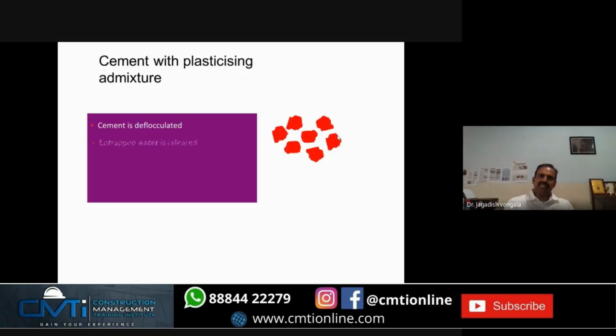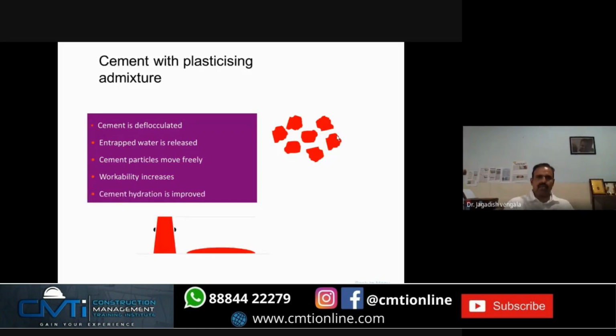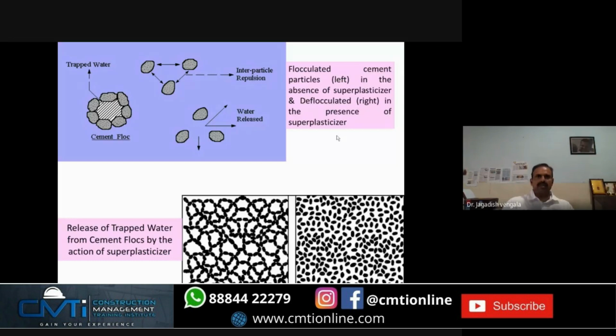So by adding plasticizing admixture to the mix, the entrapped water is released and cement particles will move freely. Workability increases. When you have more water available for the hydration, your hydration products also get improved. This is another picture. Just to mention once again, when you add water to the mix, the cement flocks will form. When you add the chemical admixture, it releases the trapped water and it becomes more workable.